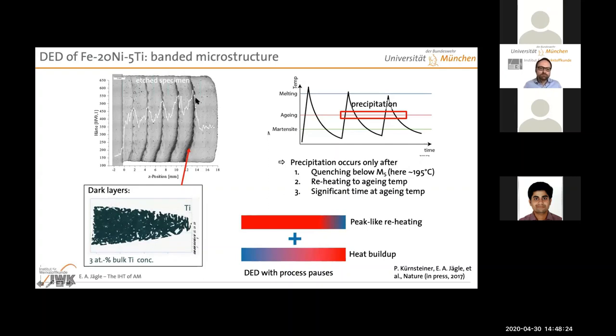Here, this is, I would say, an imperfection of the DED process. The DED process is, of course, way less a near net shape process as compared to LPBF. And basically, if you're targeting a cube, what you always get is something with a quite strongly curved top. This is what you see here as well. So these are the sample contours. So that is one contribution. Another contribution could, of course, be the increased cooling due to radiation at the sample edges. How much of it is what? I'm not 100% sure, but I think it's mostly this. If you would zoom in here, unfortunately, this is a relatively low magnification micrograph, so I can't zoom in. But if you would follow this dark layer, it really is following one particular deposition layer.